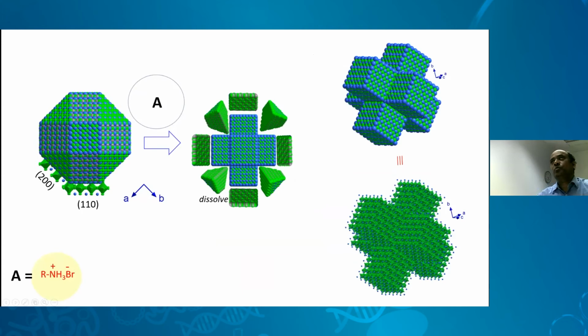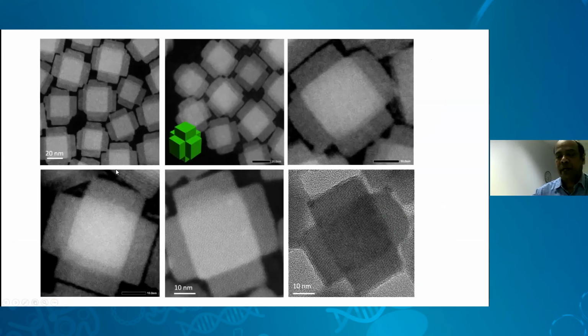So these structures turn out to be a hexapod structure, an arm structure. But this is nothing but a combination of several cubes, you could see. Therefore, the facets which remain outside in each case are nothing but the same facet as that of the cube. Now, on the bottom, you could see the octahedral model that is replicated for these perovskite materials. The images are so beautiful. All these are the 6 arm structures coming from the same polyhedra when treated with the primary ligand A.